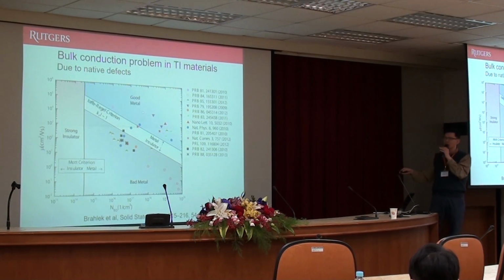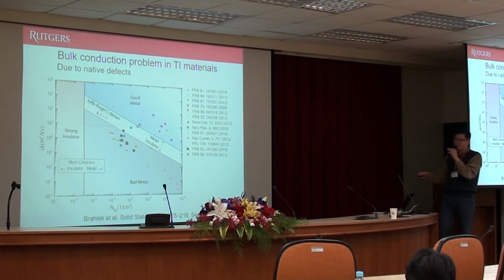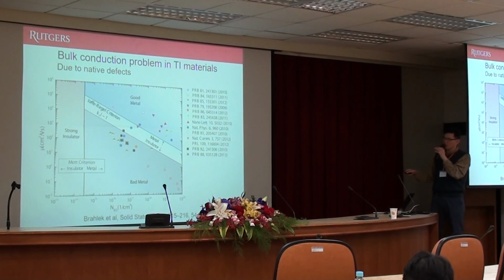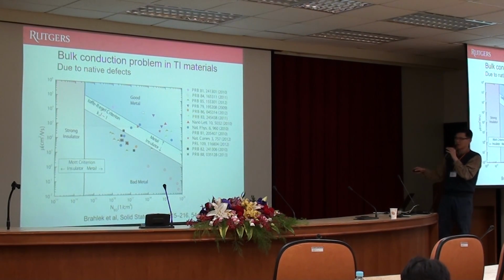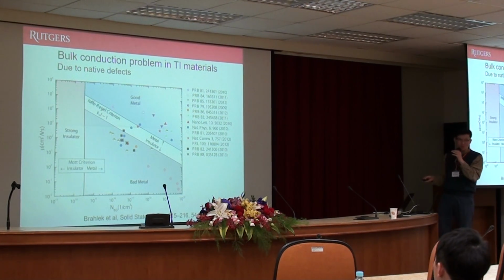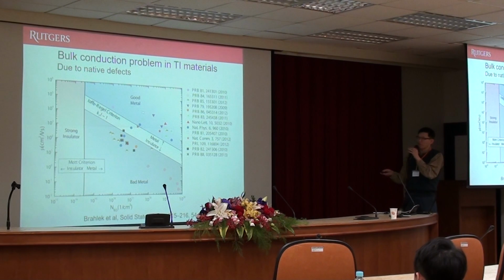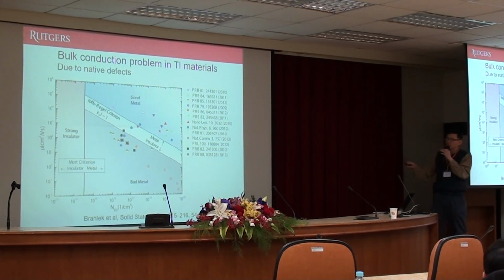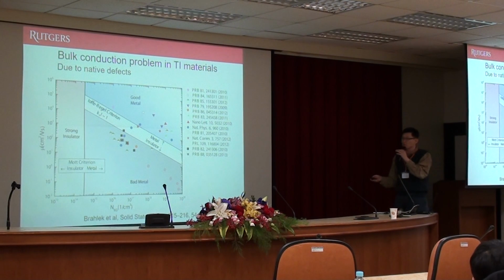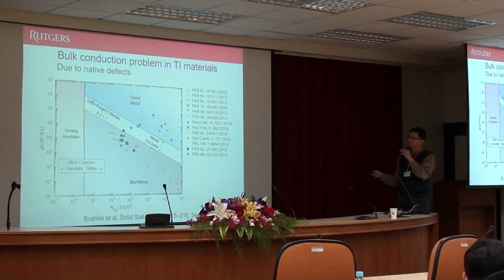But this is quite a dirty state, highly disordered. It behaves as insulating, but it is not really nicely exponential. The resistance does not increase exponentially like a regular strong insulator. But this is where these so-called bulk insulating samples actually are. So you can see that this native defect problem is quite fundamental. How can we beat this? Somehow these materials fundamentally have native defects. You cannot beat it. So okay, we are doomed. Okay, yes.